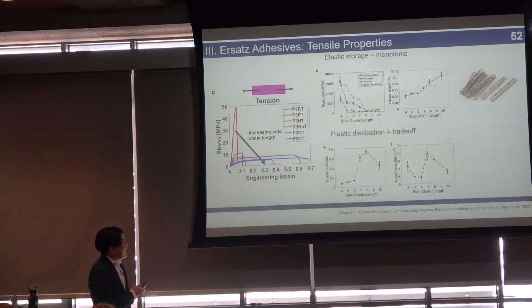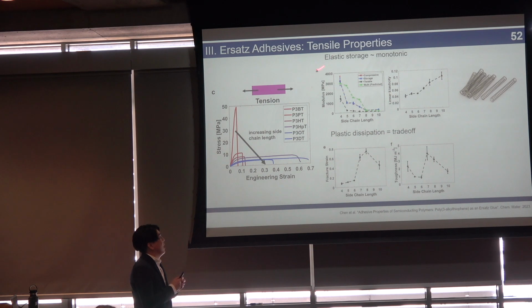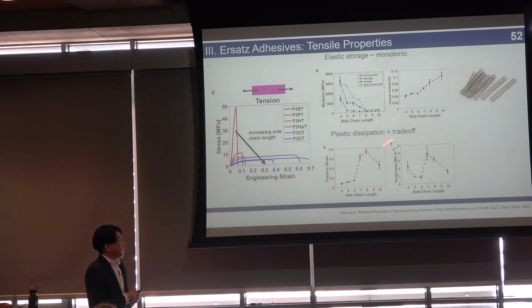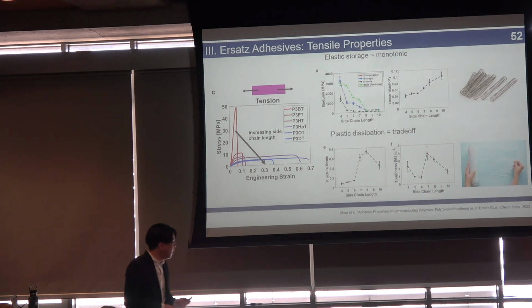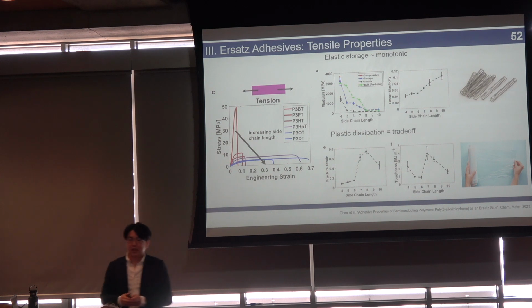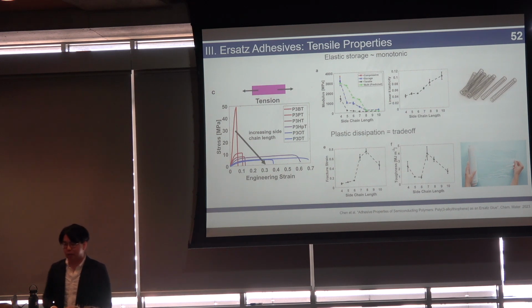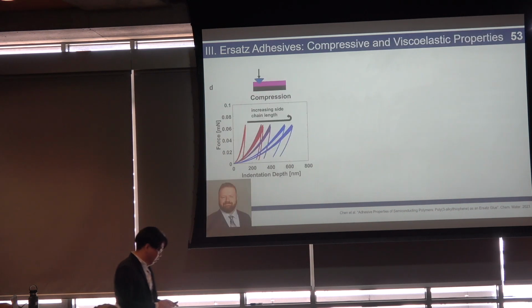But plastic dissipation of energy instead of elastic storage of energy requires a trade-off. And we see that, in particular, the best fracture strain is not at the longest side chain length, like you would expect. It's actually at n equals 8, so P3OT over here. You could think of this plastic behavior as, of course, behaving like saran wrap. So we worked with a collaborator at Arizona State University to understand what's going on here.